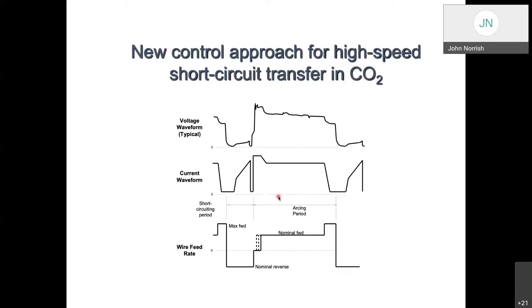So we looked at ways of trying to improve the speed of operation. And we were able to do that by changing the wire feed rate as well as the voltage and the current. And in fact, what we did was reverse the wire feeding rate during the short circuit. You can see from this graph down the bottom here, it's a schematic of how we reverse the wire feed rate when the short circuit occurred, and then reinstated it at the end of the short circuit.